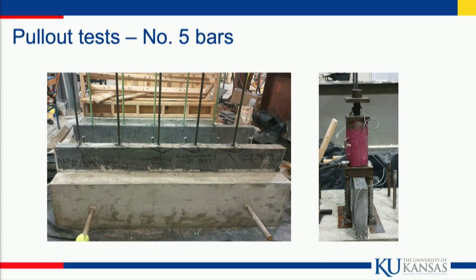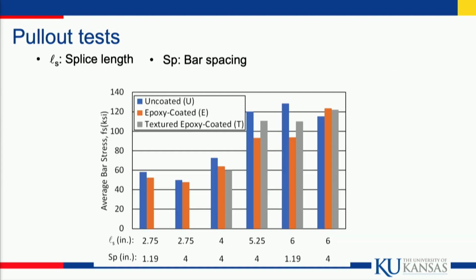Okay, this is the test we did at KU. It's a really good bond test. It's a pull-out test because you don't actually push on the concrete, you push on the precast slab. So both the UHPC and the test bars are in tension, much more realistic. What do we get? Well, we tested many combinations of splice length and spacing. Let me direct your attention. Blue is the uncoated bars, orange are the epoxy-coated bars, and gray is the textured epoxy-coated bars. Notice that the textured epoxy-coated bars come up and don't look too different from the conventional bars, and that the epoxy-coated bars in most cases are weaker, but they acquit themselves quite well, especially look at the last series where they're actually stronger. Pull-out tests are not good for design, though.